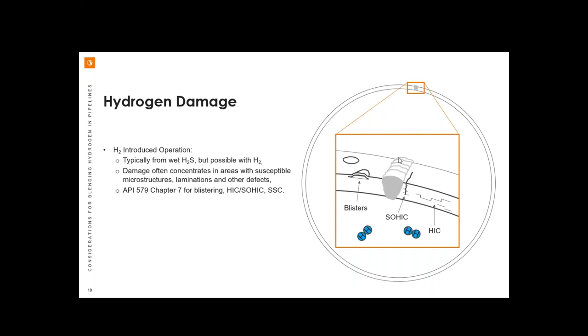The first would be HIC, or hydrogen-induced cracking. Remember, we have these single hydrogen atoms that are wandering around inside the steel, and they can pile up in areas where we might have a lamination, and then recombine in some cases to diatomic hydrogen, which is a lot bigger molecule. And so we're really forming a wedge here that can start to grow cracks. And if they're extensive enough, they can grow into each other and form a stepwise pattern. Similarly, we can have SOHIC, stress-oriented hydrogen-induced cracking. Typically we would look for this in a heat-affected zone near a weld. That's a microstructure that can become susceptible to hydrogen recombination because it has an applied stress level. In this case, we have a hoop stress that's working to pull the weld apart. We would see the heat-affected zone near the weld metal, and we'd see cracking that was perpendicular to the stress.